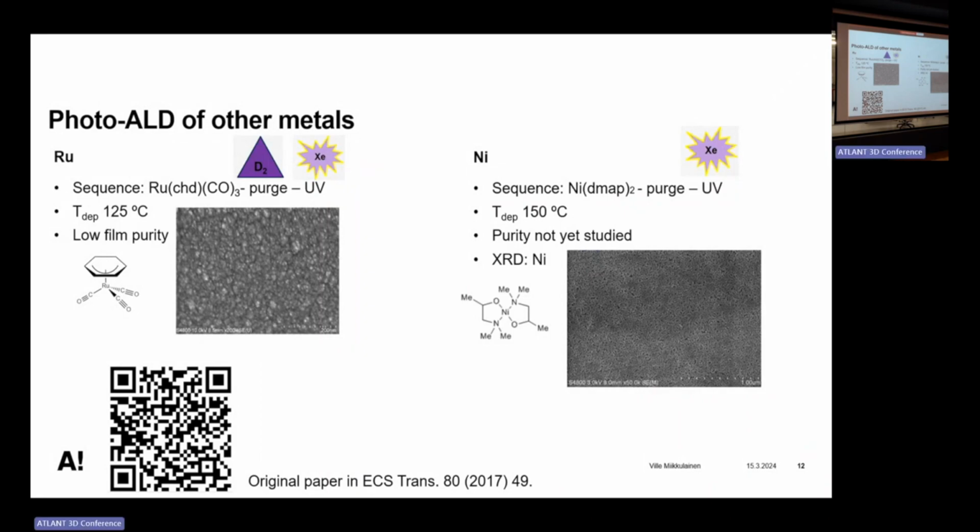That works at 125. Above that, it starts to thermally decompose. It deposited film, but it was quite full of impurities, so we didn't continue that.